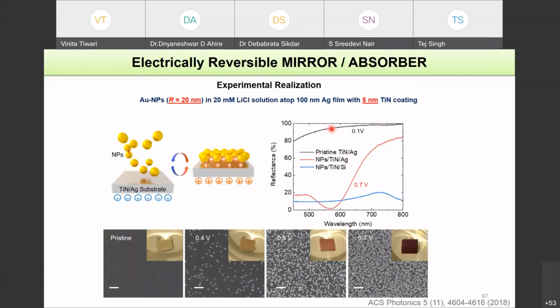Okay. And then when you keep on increasing the potential to say 0.7 volt, more number of nanoparticles, gold nanoparticles, come and sit on this silver substrate, and you see a dip in the reflectivity. And this is where you can switch between a highly reflective state to a low reflective state or an absorber state just by changing your potential from 0.1 volt to 0.7 volt. And this is what happens practically.